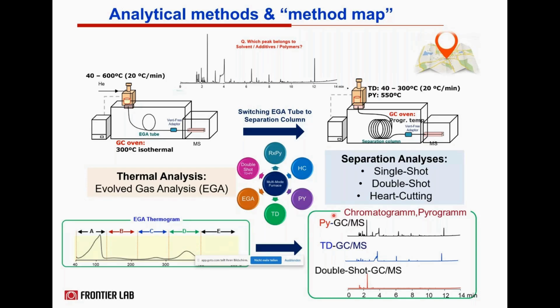To implement TD-GC/MS or Py-GC/MS or a combination of these analytical methods, so we are on the right-hand side here, a GC separation column is then installed and a GC oven program is used. Pyrograms or TD-GC/MS chromatograms are then obtained, or a combination of thermal desorption followed by pyrolysis. We call it double shot technology. Heart cutting is a thermal slicing of the thermogram. So in this example here, we can heart cut fractions from A to E. Up to 8 steps are possible, and the selective sampler, which I introduce later, is a great tool to perform this heart cutting automatically.